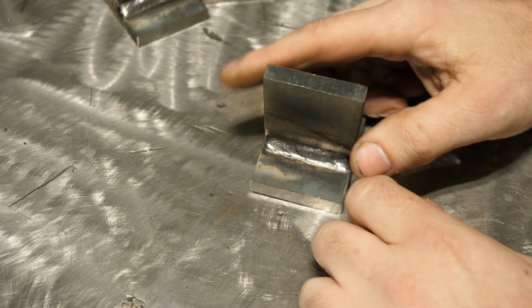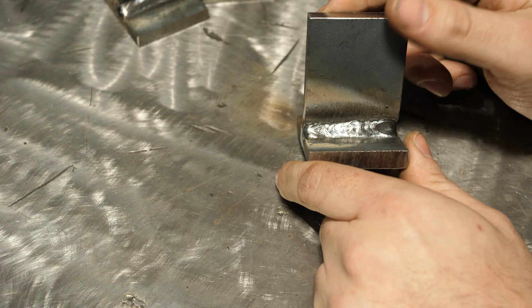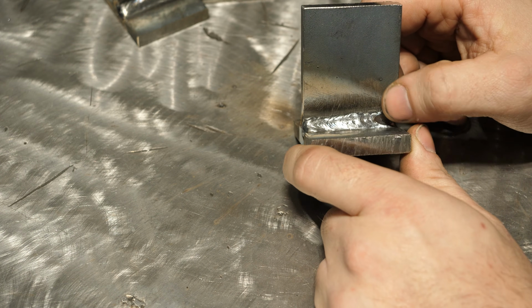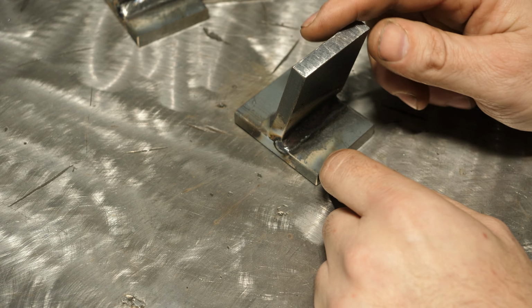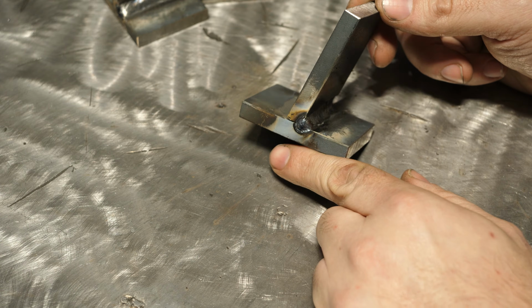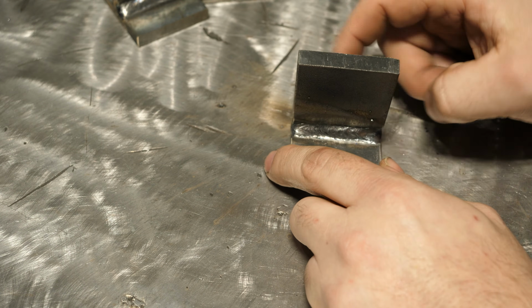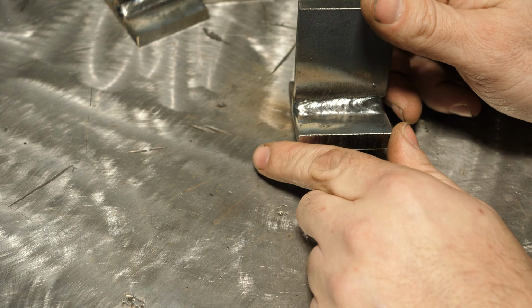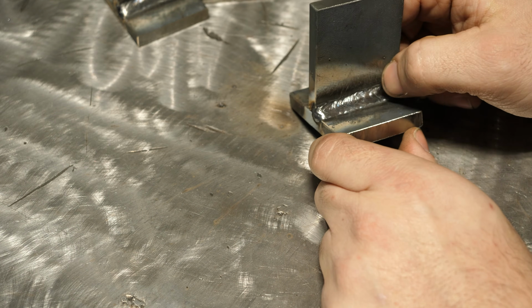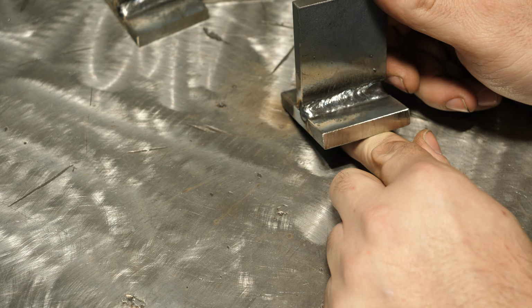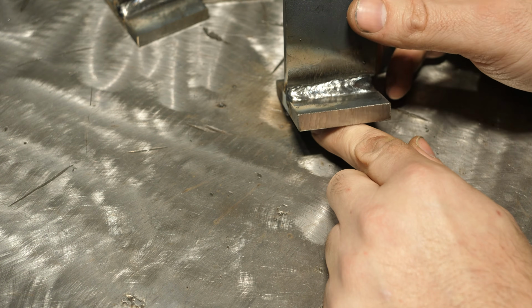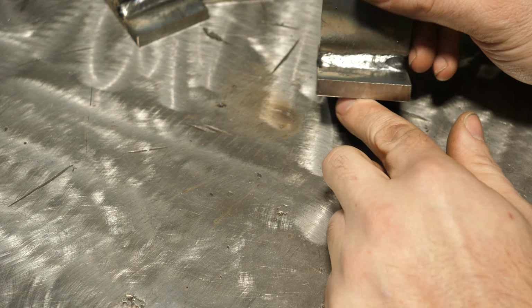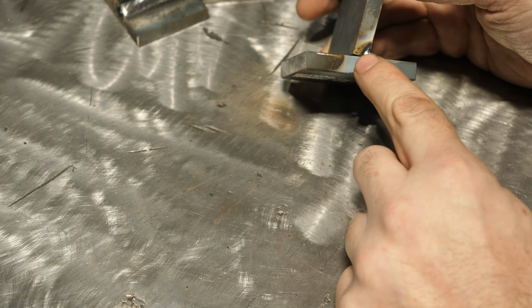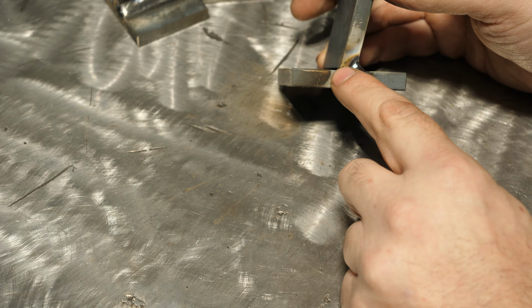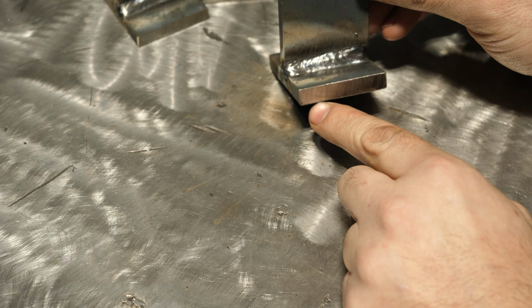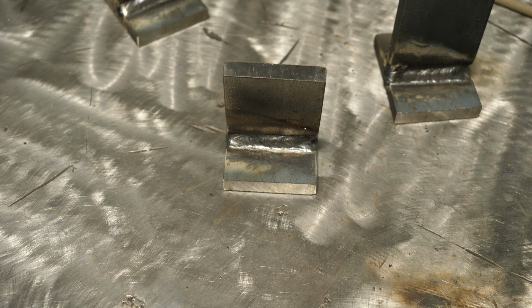Now this guy, I learned a valuable lesson that I often forget. Even though this was clamped when I welded it, as soon as I was done welding it, I unclamped it, sat it on here, and as that weld cooled, look how much that pulled. Pretty wild. And as part of this test, I don't tack anything. Had I tacked this and kept it clamped a little bit longer, this would have never happened. But this rod, due to the metal deposition rate, has a really bad tendency of shrinking a fair amount, and that will pull things. So this one, I think we're going to press it in a shop press, but the odds of a failure, I would say, is higher because it's going to have to stretch that weld a lot more as it closes that gap. But that's what we got, so let's start out with breaking this guy with the arc strike towards the face.